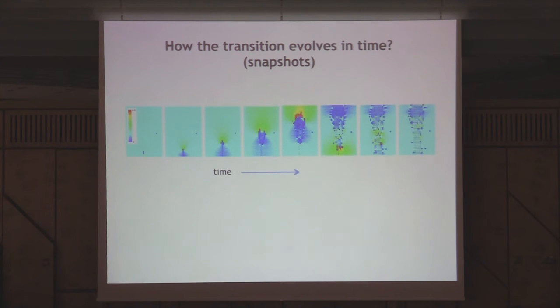So now the thing branches out, and you have a filament that grows and becomes thicker and thicker. It grows and gets to the other side. Once it gets to the other side, all this region is a nice metallic region. Then the filament realizes that its state is not so conducting, so it reverses direction and breaks all this part, and then this relaxes further until you get a more or less homogeneous filament. You switch off the voltage, and this goes away.